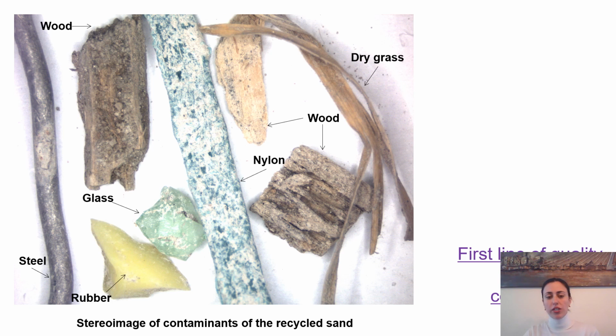So here you can see the contaminants that we found in the different groups or streams which were studied: steel, rubber, glass, wood, nylon, dry grass, and so on. However, these contaminants were up to 5%, and this is not that worrying, considering that this material is not washed at all at the recycling plant.